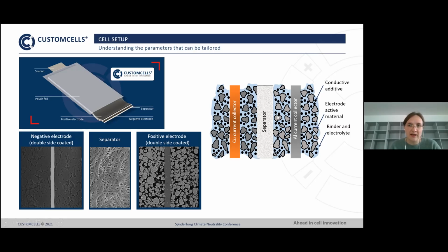Everything in the cell, every pore, and also the separator, is filled with an electrolyte that also contains lithium ions, and that helps to close the lithium ion conduction pathway. The electrons will be going from the outside contact from negative to positive, so that there are two conductive pathways. One is the electron conductive pathway, and the other is the ionic conductive pathway.